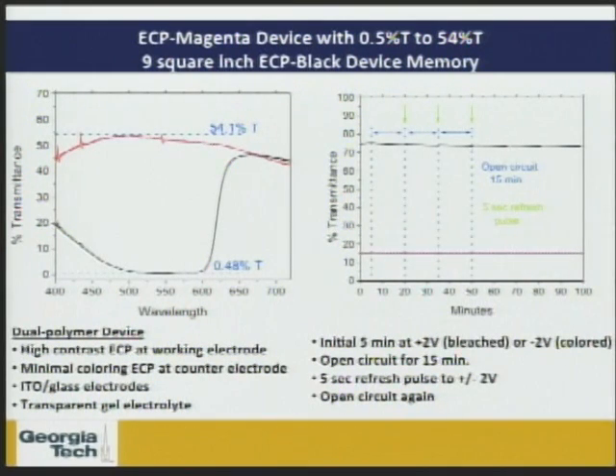The other aspect then has to do with energy. And I'll just focus in on the right-hand side here today to point out that as these polymers are films on electrodes, then they have electrochromic memory. In essence, what we're doing here is we are setting our polymer either in the absorbing state or the transmitting state. We are giving a 5-second pulse of 2 volts, and then we are sitting at open circuit for 900 seconds. And we are holding that color, and depending on whatever voltage we have, we could set any level of transmission in between here and have that stability.